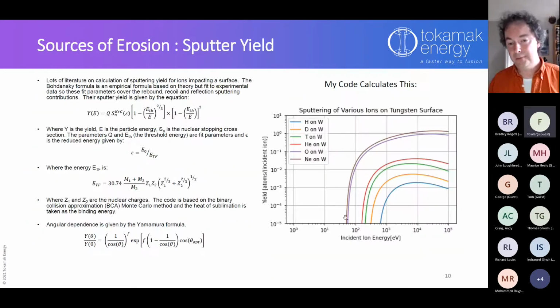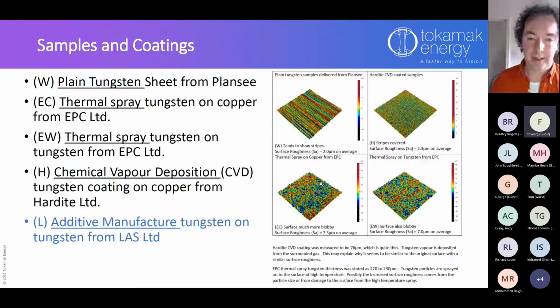So that's our theory that we've developed, and I've got a computer program that will predict this stuff, but is it correct? So the rest of the talk is telling you about some experiments that we've done to see if it actually is. So I've had some samples made. We've got plain tungsten, we've got a tungsten coating with a thermal spray, we've got a tungsten coating with chemical vapor deposition, which is a bit thinner, but it's a more compact coating. And then we've got laser additive solutions, that Bradley works for, has made us some additive manufacture samples with tungsten.